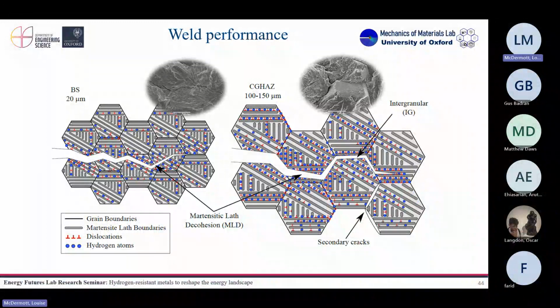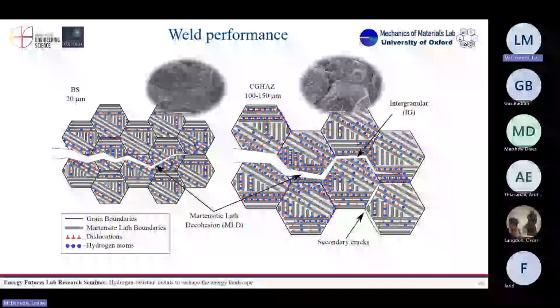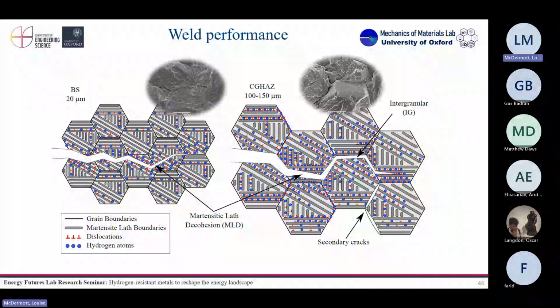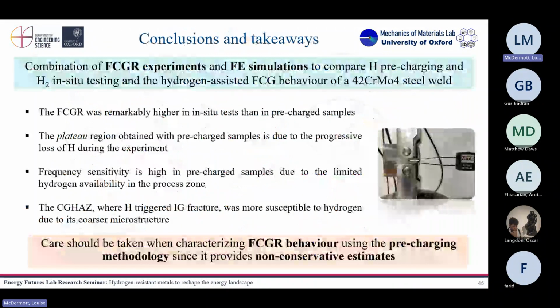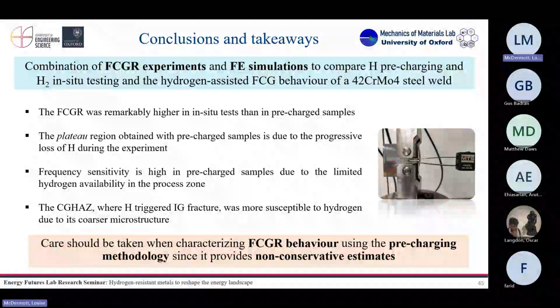So we had less density of interfaces there, so hydrogen was very prone to embrittle and make cracks grow through those internal interfaces. While here it was a bit different. We saw that the cracks could grow transgranular and not intergranular. Okay. So basically, be careful with welds, because when there is hydrogen around, they become even more brittle than they are. Okay. So that's basically the main takeaway.